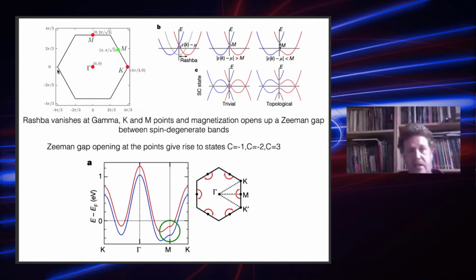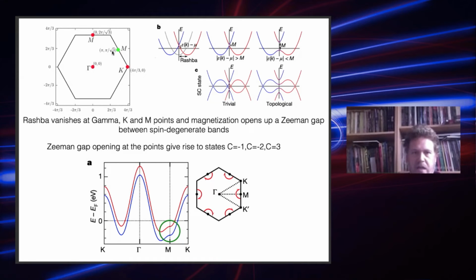So here, because this is a triangular lattice model, the Brillouin zone is a hexagon, and it turns out that there are three special points in the Brillouin zone where the Rashba spin orbit coupling vanishes. So the gamma point, K point, and M point. And wherever the Rashba spin orbit coupling is vanishing, we see that there is this Kramers type degeneracy. So locally, the band structure near any of these special high symmetry points looks like this. And of course, when we now add the magnetization, we open a gap. So we are getting rid of the Kramers degeneracy, and when we push the magnetization to even larger values, we have schematically this type of band structure near these high symmetry points.